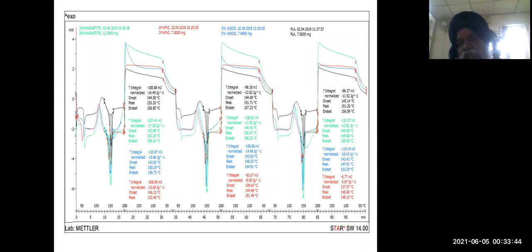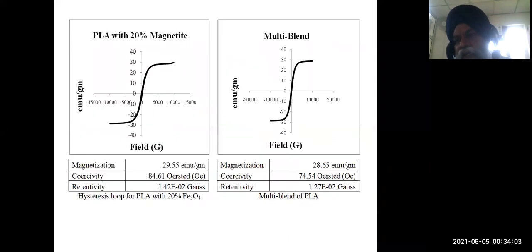Then we tried to see the thermal stability of these tiles also, from room temperature to high temperature, let us say 200, then from 200 to room temperature. Similarly, in the hot zone, as well as down to -40 also. So we tried to correlate how much energy it will be absorbing in the heating cycle, how much energy it will be releasing in the cooling cycle. Then again their magnetic properties, right? How much retentivity will be there if I switch off the magnetic field, for how long will this tile stick over there, right?